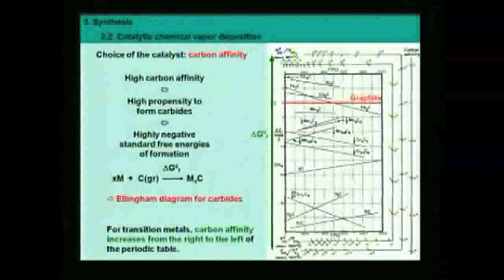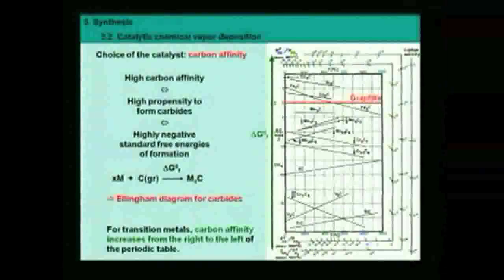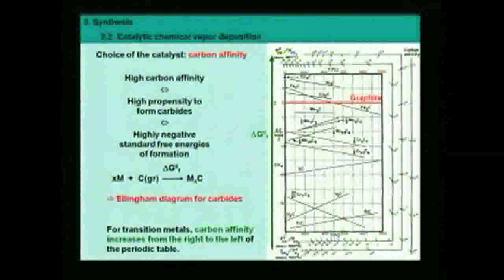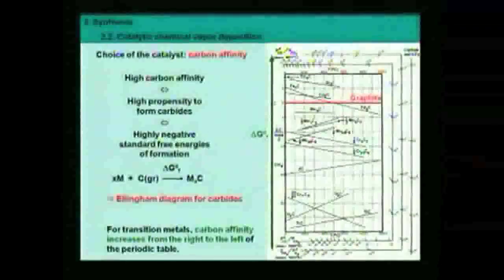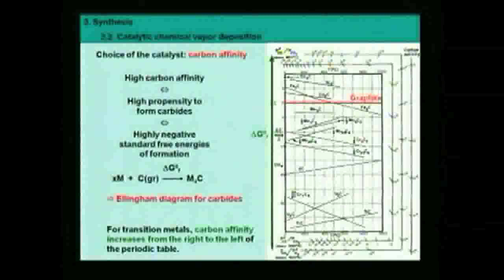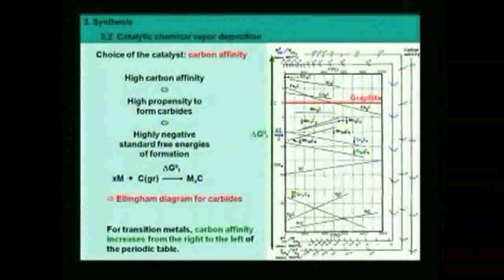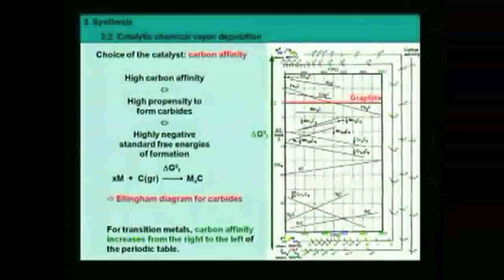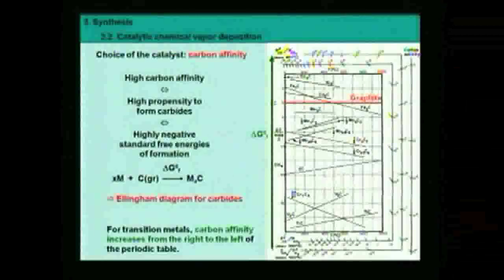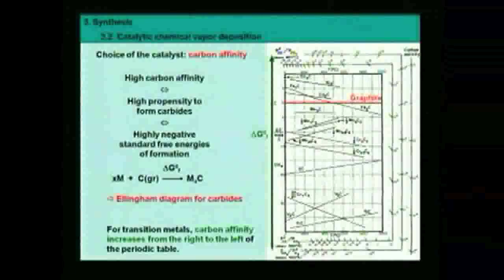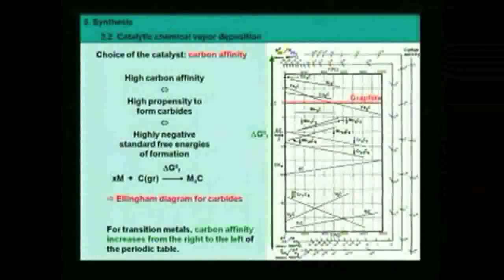If we plot those formation free energies as a function of temperature, which is again an Ellingham diagram for carbides, we find again graphite here with a free energy of formation of 0. And what we observe is that different elements can form different carbides, and those carbides have different stabilities. The most stable carbides, of course, are the ones here at the bottom, the ones with very negative free energies of formation. Here, you also observe that these elements are elements at the left of the periodic table, like before, for the dissociation properties.